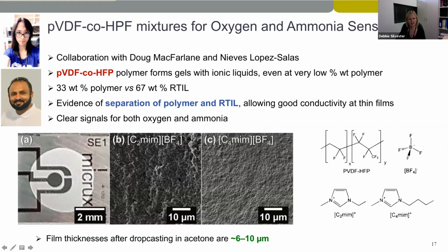And here you can see the SEM images of the polymer on the surface. And if you look closely, you can kind of see some porosity of these gels. And what it appears is happening is that the polymer is acting more as a scaffold, and the ionic liquid is flowing more freely through the scaffold. And this was actually quite interesting because it allowed us to go to very thin films of about 6 to 10 microns and still get very good conductivity.